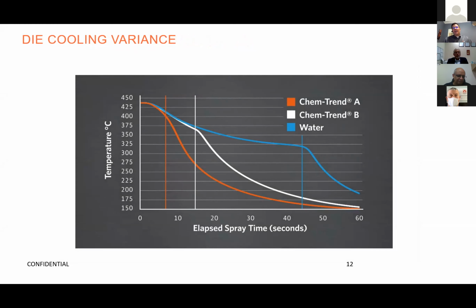You'll see that as these materials spray, they hit the Leidenfrost point, and you can see it. Once you hit that point, you get dramatic cooling. You can see here in the white one, especially Chem-Trend B, it hits the Leidenfrost point and we get dramatic cooling. So you're going to watch this get sprayed. Once again, this is a laboratory test, so to be clear, I'm not saying that if you start spraying a die at 425 degrees with die lubricant A for 10 seconds we'll take you down to 325. This is a relative laboratory test. But a difference like this has a significant impact on your process and your spray time.